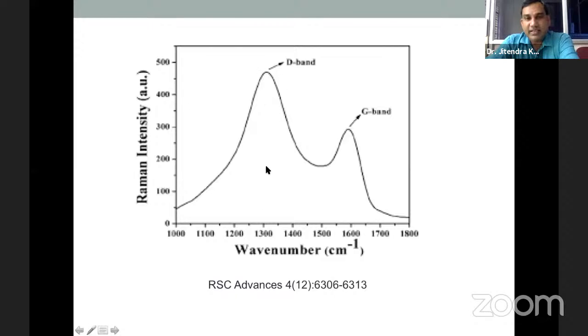So the peak intensity or height depends on the availability of sp2 or sp3 structure inside your compound. And sometimes the primary compound you have generated by Raman, after some time, after the tribological test, these peaks can be shifted. So this shift of the peak also gives you better results. Because of that shift you will get a lower coefficient of friction or high wear resistance, or higher wear or higher coefficient of friction. So this peak analysis is very important. The sp2 sp3 structure we can get from this Raman intensity versus wave number.